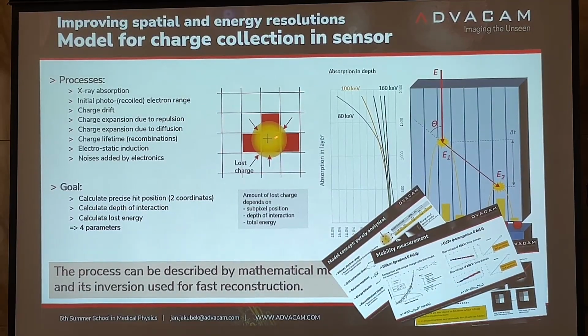Very often it happens that our photon would hit a point in the pixel which is close to the border of the pixel. And then part of the signal would be detected by neighbors. So instead of having one pixel responding, we would have several. So we would have a cluster. And in such a cluster, each pixel would give us the amount of charge, how much signal for that one event is seen. That means that for that single event, we have 4 numbers measured, and it allows us to calculate 4 other things. For example, we can calculate the precise hit position in X and Y with better precision than one pixel. So this would give us 2 numbers. And then we can calculate the depth of interaction, and we can calculate the energy which was lost.